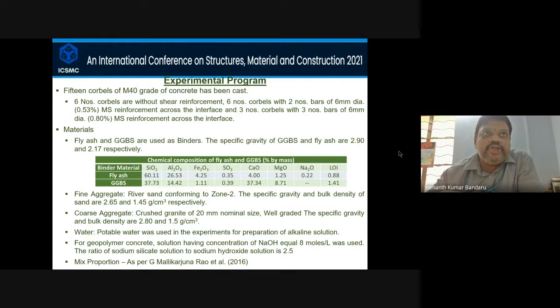The materials used are fly ash and GGBS as binders, and the chemical composition is shown in the table. The fine aggregate conforms to zone 2, and we have taken river sand. The coarse aggregate is crushed granite, well graded. Potable water is taken for the preparation of the alkaline solution.